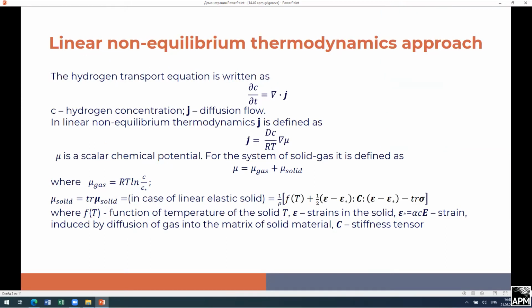We use the linear non-equilibrium thermodynamics approach, where we write the hydrogen transport equation as a divergence of the flow. And in linear non-equilibrium thermodynamics, this flow is defined as some values multiplied by the gradient of scalar chemical potential. For the system of solid and gas, this potential is defined as the sum of the chemical potentials, and as the chemical potential of the solid is normally a tensor value, we take the trace of this tensor as we consider the diffusion which propagates in all directions.